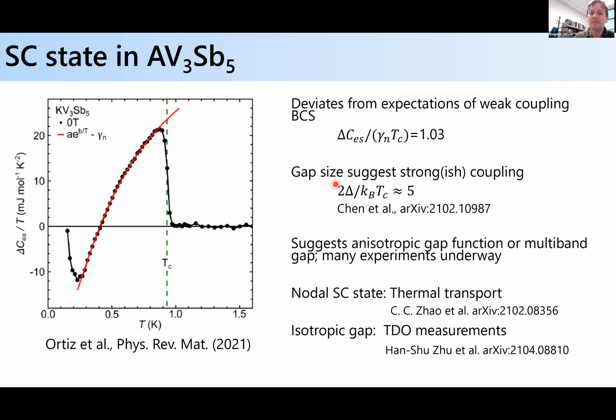But at the same time, STM is able to resolve the superconducting gap, and it's roughly about 0.5 millivolt. So if you look at the 2Δ over kBTC for these systems, it's on the order of 5 or 6. So it's kind of strong-ish coupling, moderately strong coupling, however you want to describe it. But the combination of these two things would suggest that you either have an anisotropic gap function or a multi-band gap, so more than one gap.